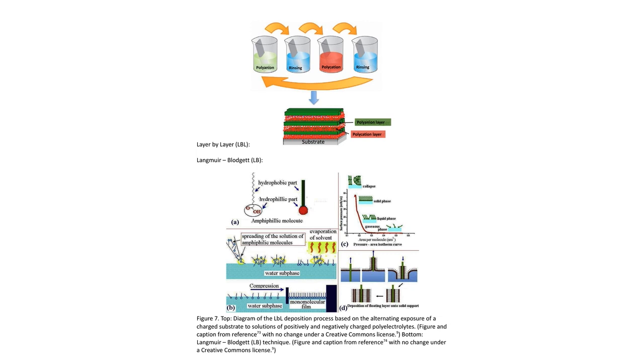The first is the layer-by-layer, or LBL method, where a charged substrate is alternately dipped into solutions of positively and negatively charged polyelectrolytes, building up a multi-layered film one layer at a time. The second is the Langmuir-Blodgett, or LB technique, where amphiphilic molecules, molecules with both a water-loving and a water-hating end, are spread on a water surface, compressed into a monolayer, and then transferred onto a solid substrate.